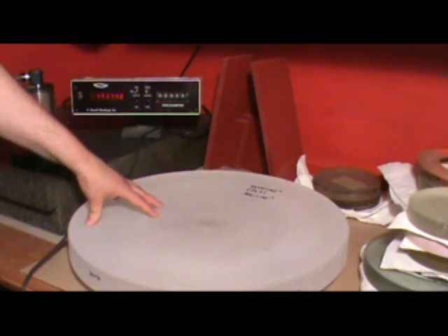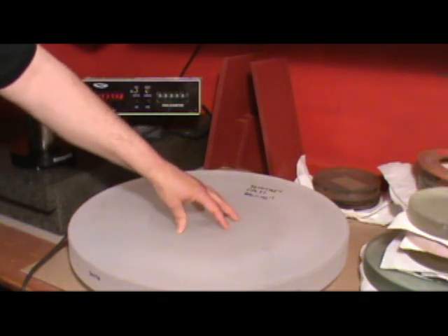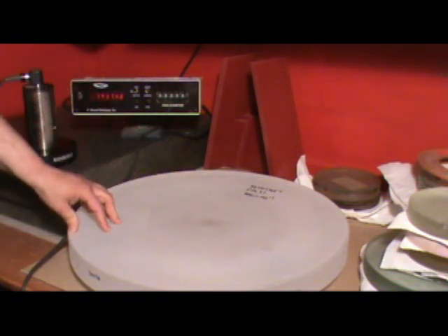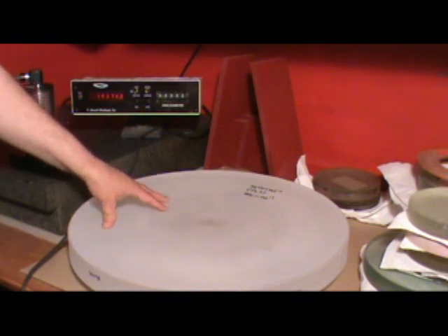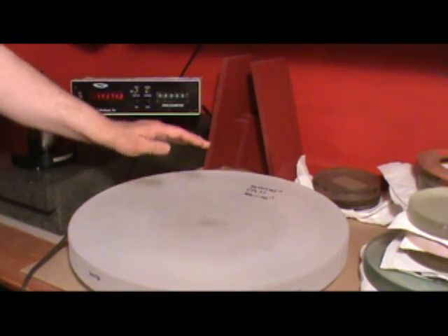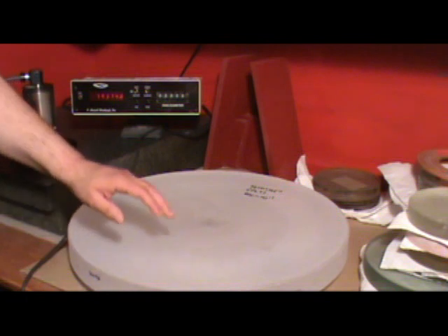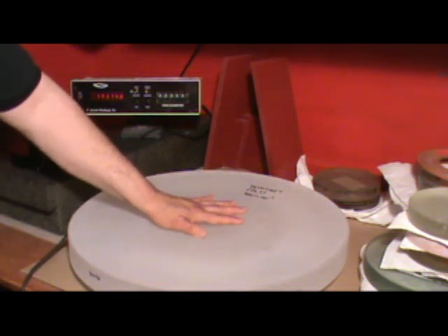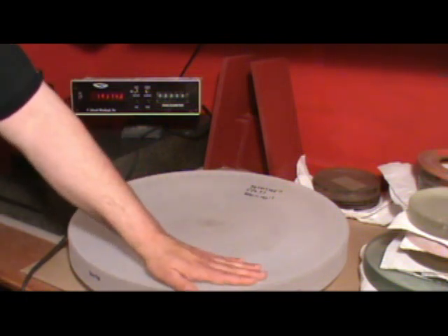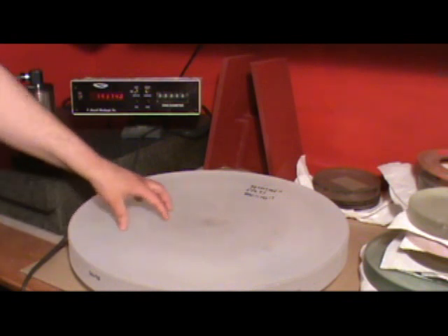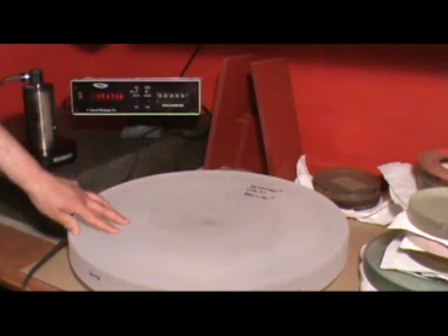And it's important that we get close to our real target, which is 140 inches, and thus I want to know the radius in the center, the middle, and the edge, so that I can plan my grinding accordingly and know if I have to deepen this mirror or shallow it up. If I need to deepen it, I'm going to work the center. If I have to shallow the mirror, then I'm going to have to work the edge. So knowing these three different measurements is real important.